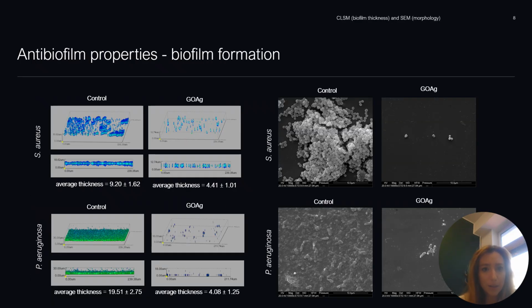The antibiofilm activity of the nanocomposite was evaluated using confocal laser scanning microscopy and scanning electron microscopy. For confocal microscopy, biofilms were stained with DAPI and with SYTO9 to minimize non-specific binding and staining and enable accurate visualization of biofilm architecture and thickness. The results demonstrated a great reduction in biofilm thickness following exposure to nanocomposites compared to untreated control. Here are the control samples for Staphylococcus aureus and Pseudomonas aeruginosa, and here are the